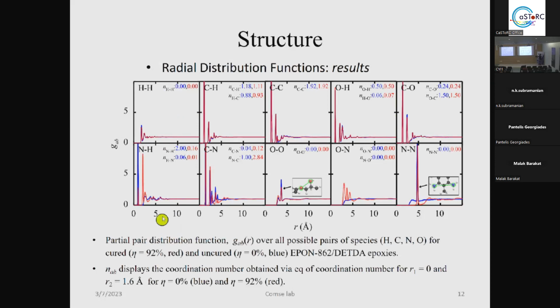With the coordination number that you see in the inset of our plots, it says how many times one atom, for example, the hydrogen first, sees another hydrogen in a covalent bond. So either in the cross-linked or the uncross-linked system, one hydrogen cannot see another hydrogen. That's why the coordination number here is 0, in contrast with other pairs. Of course, these are statistical numbers. That's why you see 1 point something. Of course, you cannot see 1 point something atom, but it's only statistical. We see some difference of structure, especially on the cross-linking atoms, on the cross-linking points where the cross-link degree happens.